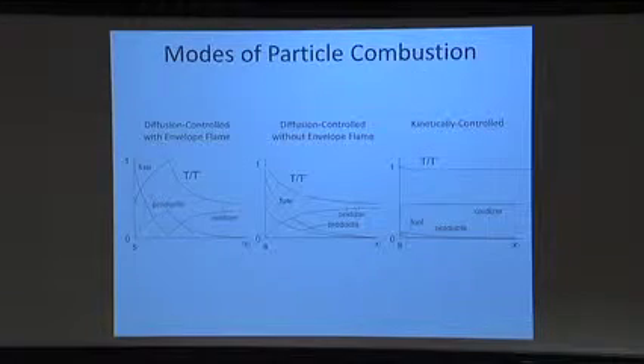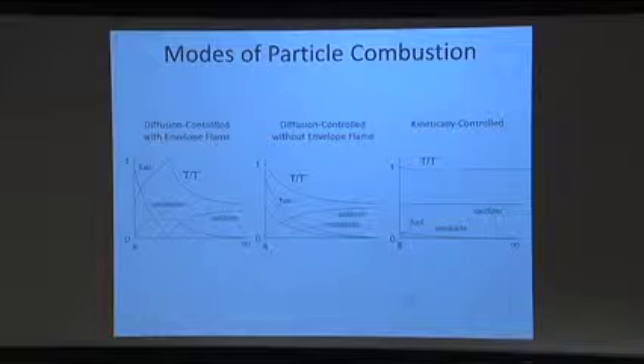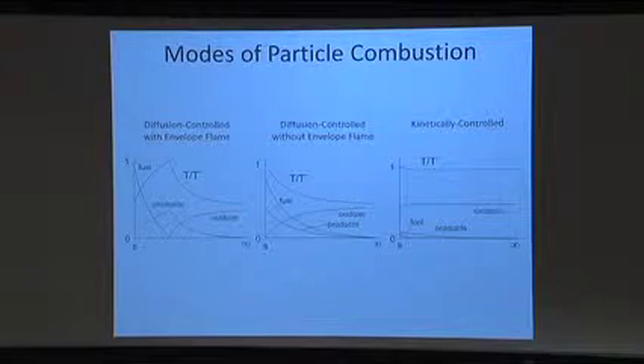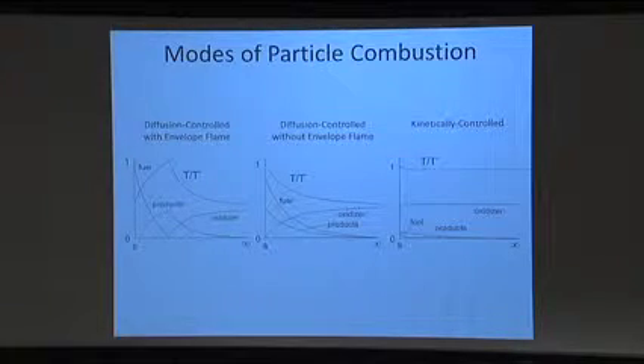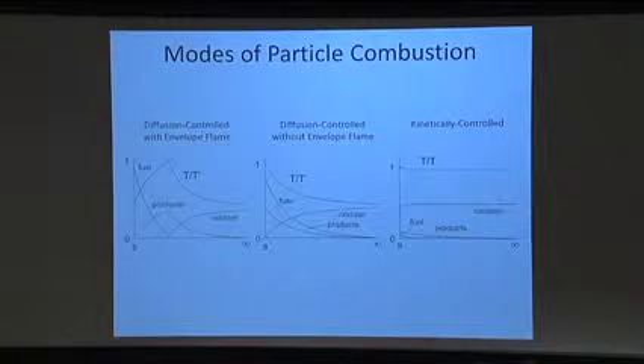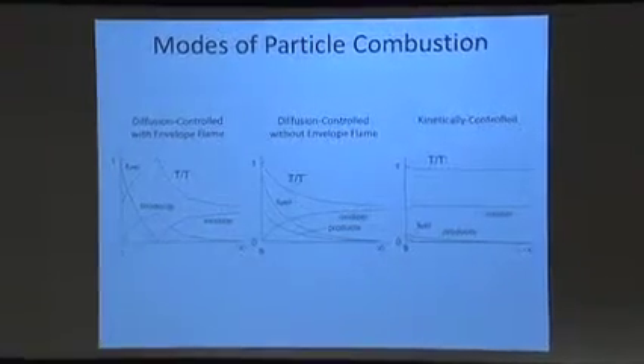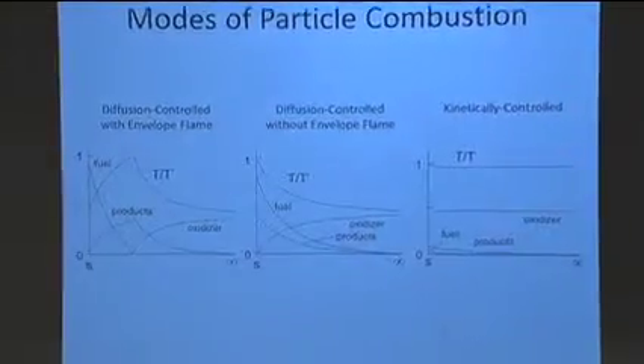As I said, as I start to shrink the particle down, what I'm going to find is it becomes kinetically controlled, as I just showed you. And when the particle becomes very small, because it has very little mass, it is going to start to assume the same temperature as the environment. So the environment now is going to start controlling the temperature of the particle.